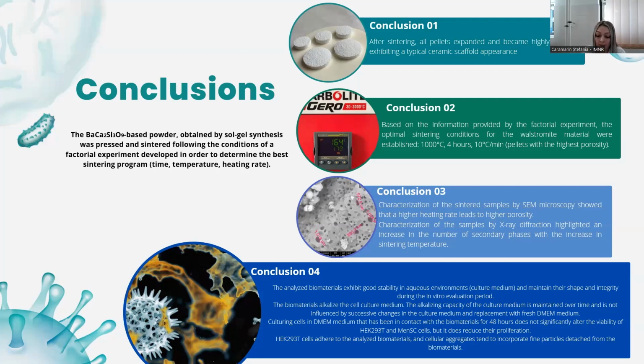But unfortunately, the biomaterials alkalize the cell culture medium, and the alkalizing capacity is maintained over time, and it's not influenced by successive changes in the culture medium and replacement with fresh medium. We concluded that culturing cells in the medium that has been in contact with the biomaterial for 48 hours does not significantly alter the viability of the cells, but it does reduce their proliferation.